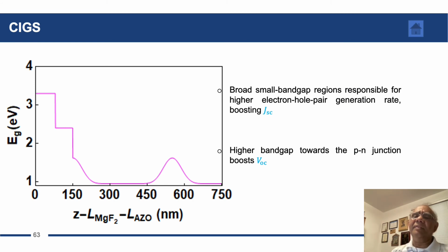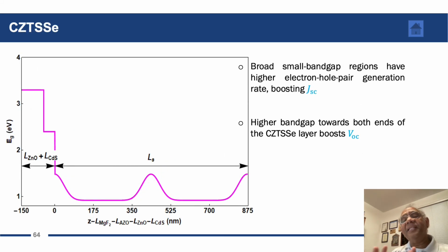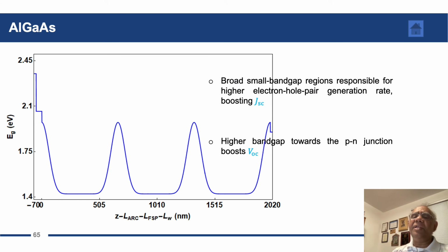For the CIGS solar cell, we found that the small bandgap regions boosted the short circuit current density, whereas the higher bandgap region near the PN junction in the photon absorbing layer boosted the open circuit voltage. For the CZT SSE solar cell, the broad small bandgap regions in the photon absorbing layer have higher electron-hole-pair generation rate, and that boosts the short circuit current density. Higher bandgap towards both ends of the CZT SSE layer boosts the open circuit voltage. The same explanations hold for the AlGaAs solar cells too.